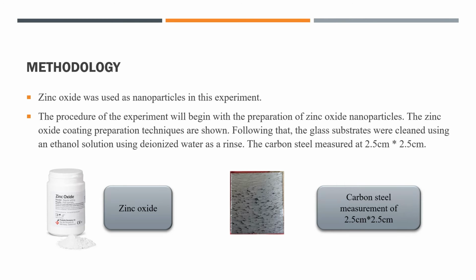As for the methodology, the preparation of materials and apparatus was carried out through a step-by-step procedure. In this research study, zinc oxide was used as nanoparticles. So, the procedure of the experiment will begin with the preparation of zinc oxide nanoparticles. The zinc oxide coating preparation techniques will be shown. Following that, the glass substrates were cleaned using an ethanol solution. Using deionized water as a rinse, the carbon steel measured 2.5 cm times 2.5 cm.